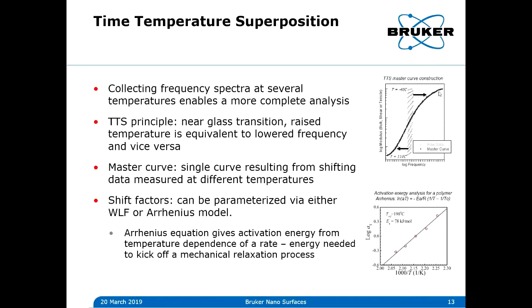And what the rheologists want to do is generate a master curve, so they get a huge range of frequency, and they know a lot about their sample and the behavior of their sample. Additionally, they can look at all of the shift factors. In other words, how much did they have to move each of these little spectra. They can plot that up, and they can use either a WLF or an Arrhenius model to analyze how those curves shifted in order to figure out, say, an activation energy for the material.